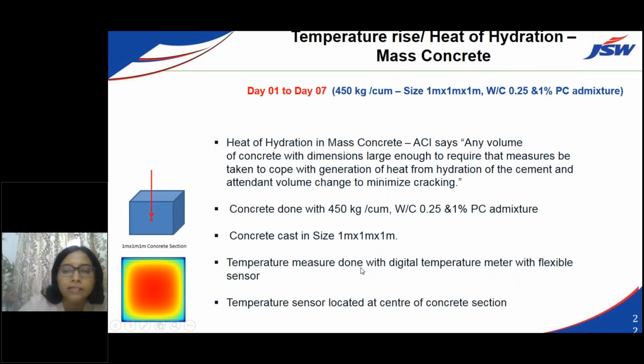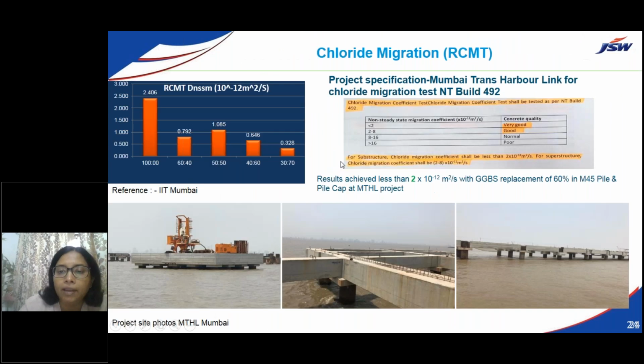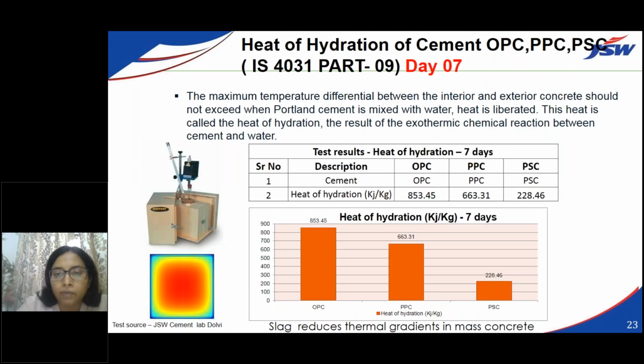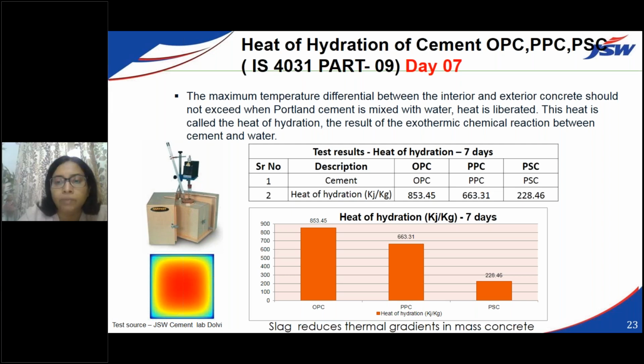The heat of hydration, I'll just briefly cover the principles in general, and we will share the detailed presentation. The heat of hydration of the products of slag are very good. Very good, it is comparatively very less as compared to products which are made with purely OPC. So we have done some tests of heat of hydration at NCCBM. Cement has given a heat of hydration of 853 kilojoule per kg, whereas fly ash is giving a heat of hydration of 663 kilojoule per kg. Slag products are giving a heat of hydration of 228 kilojoule per kg with 50% replacement.